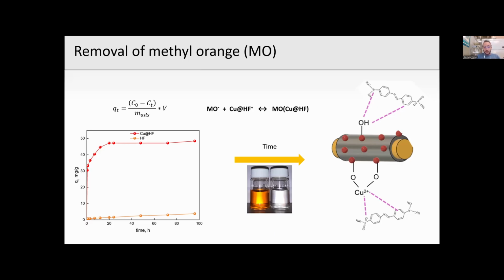In less than 1 day, 24 hours, this material is able to fully decolorize a 50 ppm methyl orange-based solution, as you can see from the picture in the middle, which is a further proof of the performance of this novel material.